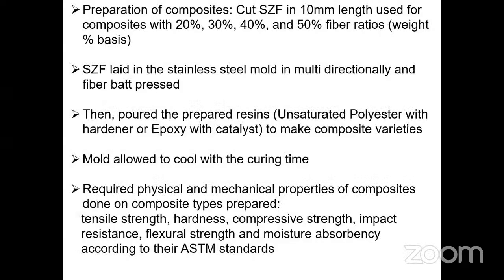First, treated and untreated fibers are cut into 10 mm length. After that, the fiber pad is made using fiber percentages. We use a stainless steel mold for this work, with two resins, polyester and epoxy. The mold is then allowed to cool with curing time. After the curing process, test specimens were cut according to ASTM standards.